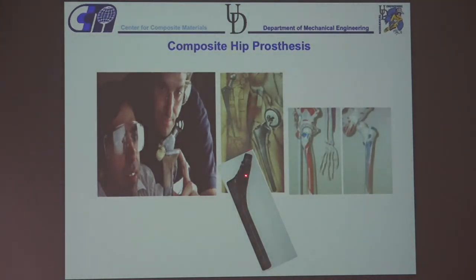And of course, thinking about applications, early on, I looked at this application where when you have shear flow, you can align the fibers in the neck region. So when you look at a hip implant, it's a very, very crude operation when people break their hips, or when you get old, you need to have a hip replaced. You have like a ball, and then you have this titanium implant. And the problem with titanium is it's too stiff. It is strong, but it's too stiff. So the load transfer is to a point and not distributed. So the bone around here does not take any load, and so it resorbs, and your hip implant will fail. And every 20 years it fails.